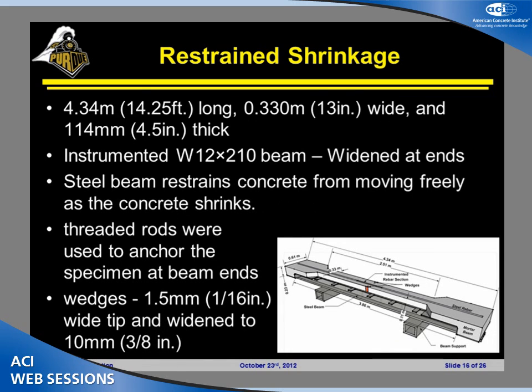So as I mentioned, here are some of the details. It's a heavily instrumented W12 by 210 beam, so this is a very, very stiff beam. It's widened at the ends and deepened at the ends to make sure we have sufficient restraint. We bolt and tie down the ends of this. And in this particular case, since we're using the instrumented bar, we put slight wedges in the center, because what we want to be able to do is control where the crack is going to form if it does form.